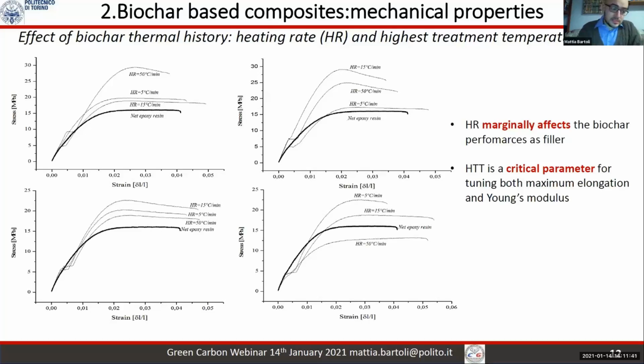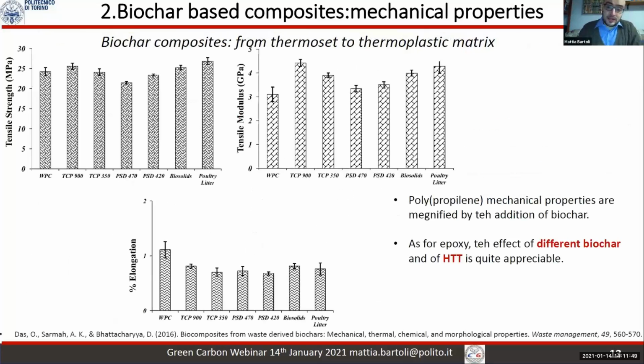But those results could be shifted from thermoset composites like epoxy, the one that you saw here, to thermoplastic ones. This is the first pioneering work published by the Bhattacharya group on polypropylene. And you can see that tensile strength and tensile modulus could be enhanced by all the biochar that you use to produce the composite, but in this case, the elongation decreases appreciably. And this is very common for thermoplastic materials. The addition of biochar in this case generally induces brittleness in the composite.